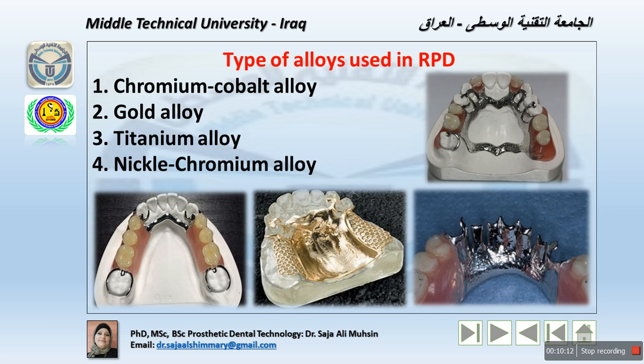And that's why we noticed most of the technicians, when they are burning or melting and overheating the cobalt chromium or chromium cobalt alloy, this will create carbon, which later on affects the final product by causing propagation of fractures. This leads to an increase of the carbon within the alloy itself. But with the proper amount of 0.4%, this will control the ductility of the alloy.